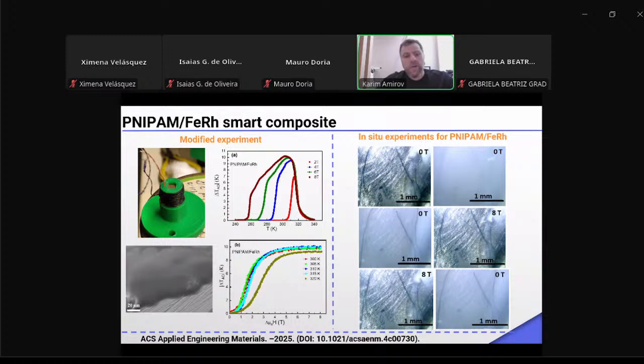composite. We construct spatial inserts, and as you can see, now we designed a new heater, a spatial holder for the sample, and as you can see, the adiabatic temperature change is also very good, about 6-7 degrees in a 2 Tesla magnetic field change. It's enough to change polymer properties. On the same image, you can also see the thickness. It's about 20 micrometers.